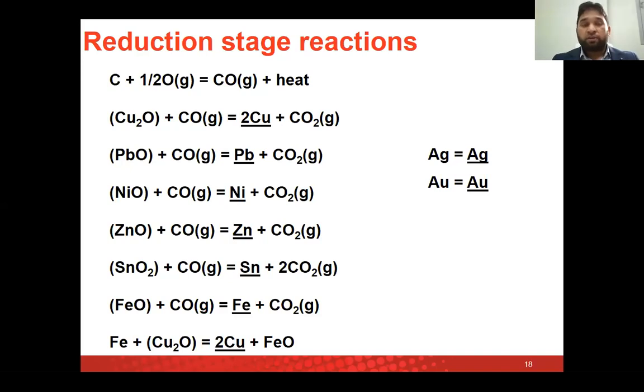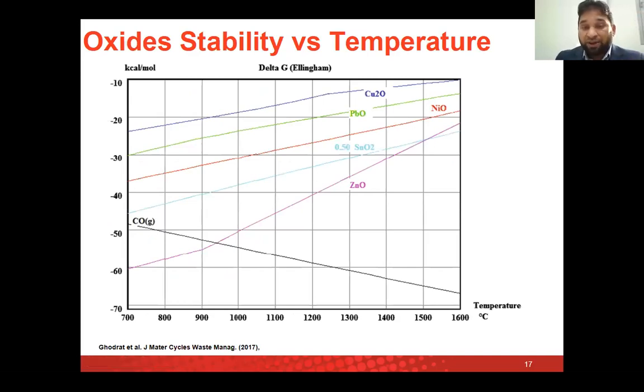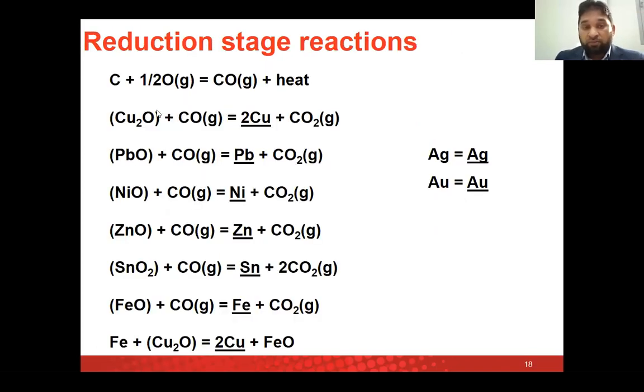In the reduction stage, you have all your input material. That input material includes your carbon coke, and you have a list of oxides that are present in your feed material. So what will happen? This carbon will react with oxygen to make carbon monoxide. When the carbon monoxide is there and you have the heat, you adjust the temperature based on this diagram. Under those conditions, the copper oxide present in there will be reduced with carbon monoxide, and you will get copper.